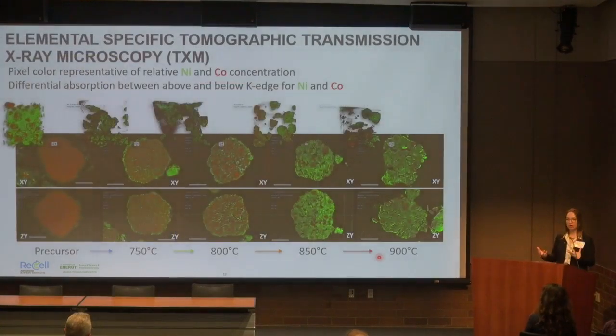And from this, we can better scrutinize this ability to relithiate and upcycle the material. Here we can see a cross-sectional slice, so this is one slice of data through the full three-dimensional volume of data. We can see a precursor material with a nickel-rich coating. At 750 degrees C, we can see a nickel-rich coating of the secondary particle, but we see some diffusion of the nickel-rich coating into the bulk. And then at higher and higher temperatures, we can see further diffusion. But with this more sensitive imaging technique, we can now see the issue here, where we see a higher nickel coating around the grain boundary of the primary particles. So it's still diffusion limited.